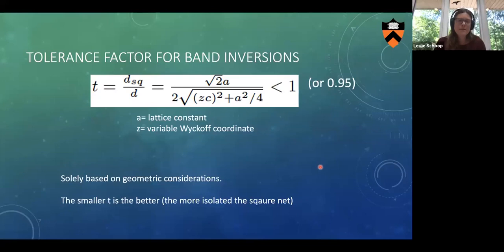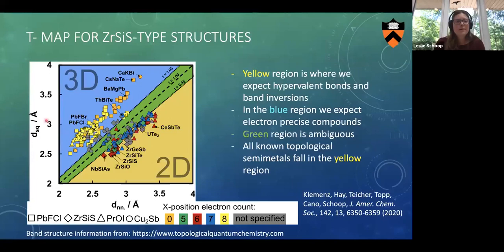So here's a plot where we plot the square net distance here, and we plot the distance to the next nearest neighbor atoms on this axis. So the way we plot it, this tolerance factor of one is this diagonal, and it becomes smaller, so more favorable to feature hypervalent bonds, towards this direction of the phase diagram, toward the yellow area, and it becomes less favorable for hypervalent bonds in this direction. And so the colors of these points now represent electron counts that we could count where it was obvious, whereas the gray ones are materials where we weren't sure. And you see the gray ones coming out everywhere.